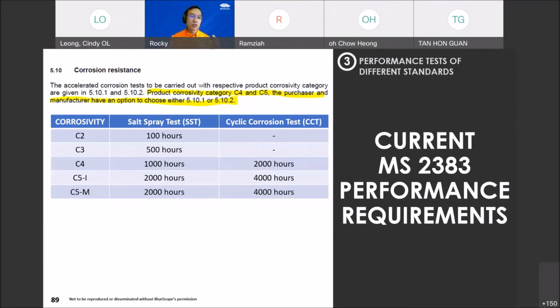But when it comes to cyclic corrosion, here you can see at different hours, C4 being 1000 hours of salt spray, and then C4 for cyclic corrosion is 2000 hours, which is double the hours. Double the hours doesn't mean the salt spray duration is higher. It actually means that it has 1000 salt spray hours, and then the rest is the mix of dry and wet cycle, depending on the type of cycle. But that is the ratio: 1000 hours of salt spray and 1000 hours of drying and wetting.